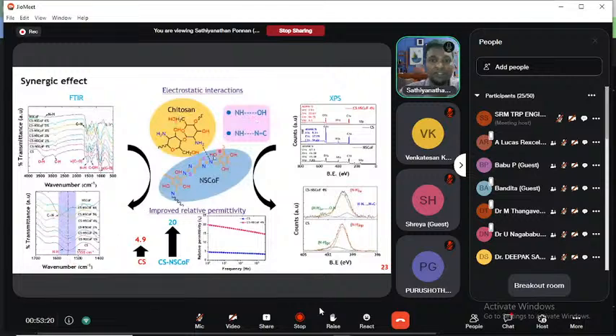So here we depicted the interaction. There is an interaction between the amine groups in the chitosan and the OH groups present in the NSCoF, or vice versa, like here this nitrogen group will interact with the hydroxyl group of the chitosan system. Similarly, this N-H...N-C interaction between the NSCoF and the chitosan systems.